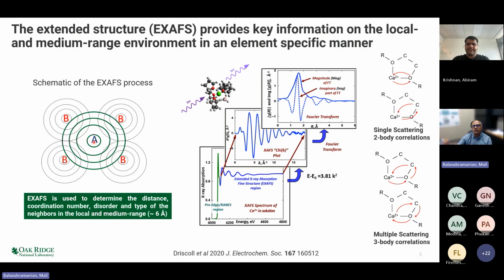As the spherical waves spread out in space, they then can interact with backscattering atoms, and a fraction of this outgoing wave will be reflected back by interacting with the potential of the backscattering atoms. So when the incoming and outgoing waves interfere in the vicinity of the central atom, you can start modulating the X-ray absorption. It is this essential nature of modulating of the X-ray absorption which gives rise to EXAFS.